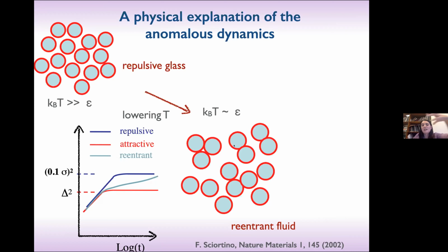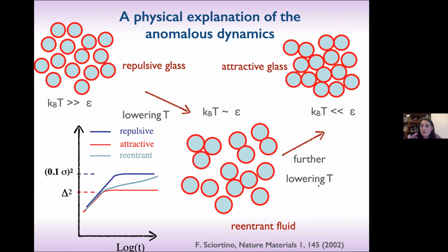And the fact that some of them, but not all of them, because these two energies are comparable, are probed, overall frees up a lot of available volume in the system, and that explains why the dynamics is re-entrant, because this fluid is much faster than this. And then if you continue to further lower the temperature, then everything will be stuck, and that's it.